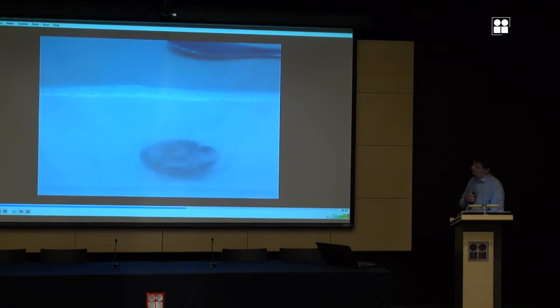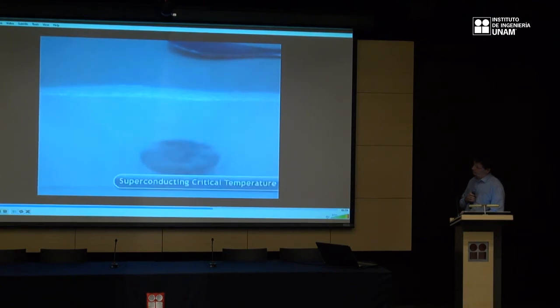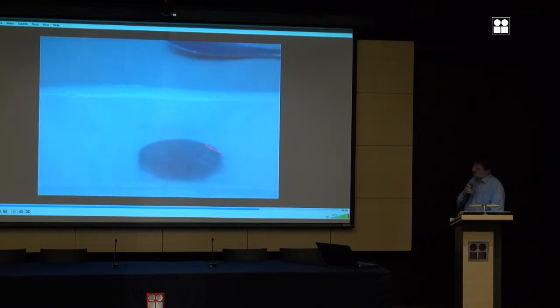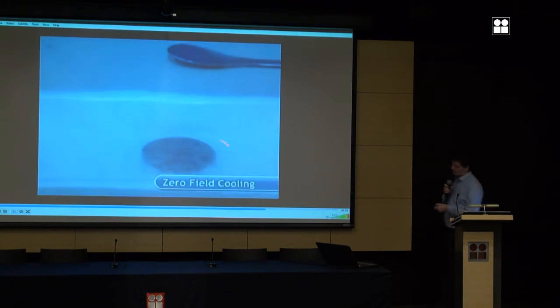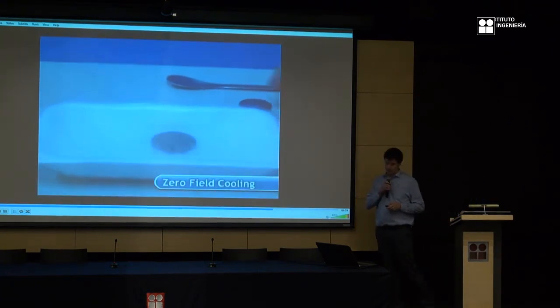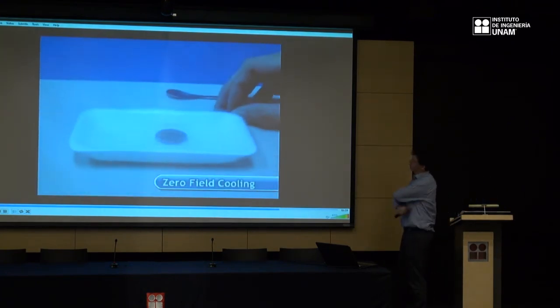When the boiling ceases, it indicates that the superconductor and the liquid nitrogen are in thermal equilibrium. This indicates that the temperature has cooled below the superconducting critical temperature, or 91 degrees Kelvin for the yttrium-barium copper oxide compound, and has established superconducting properties. Still boiling. Let's wait. When there is no more bubble, in the process of cooling, it's at the same temperature as the liquid nitrogen, 77 Kelvin. We call this cooling condition zero field cooling, which means the superconductor is cooled with no outside magnetic field influence.